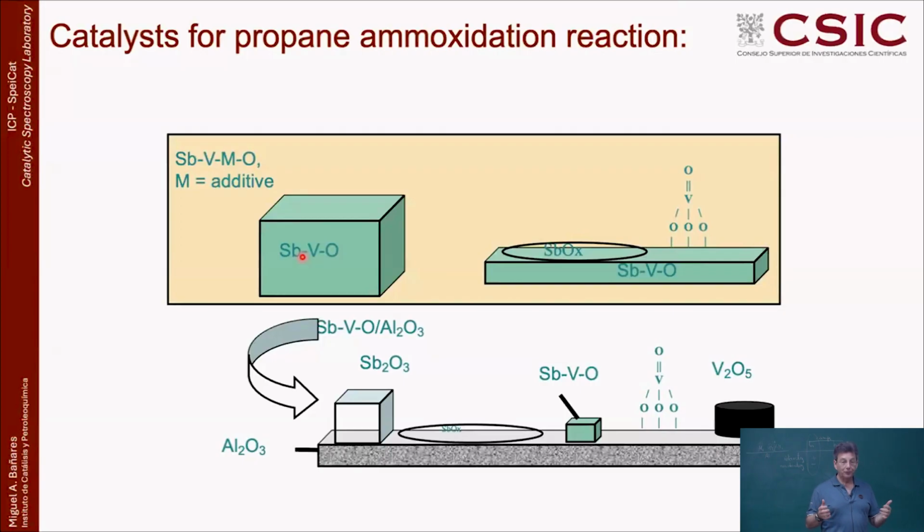So the performance of a low-loading vanadium antimony, well, you have, for instance, 1/3 of a monolayer of vanadium, 1/3 of a monolayer of antimony, that makes 2/3. It's below monolayer. So they stay dispersed. And the performance is almost the same with or without antimony, because basically the one doing some reaction is vanadium, and at this low loading, without antimony, you will get propylene, but you will not get acrylonitrile, which is associated with this vanadium antimonate phase.